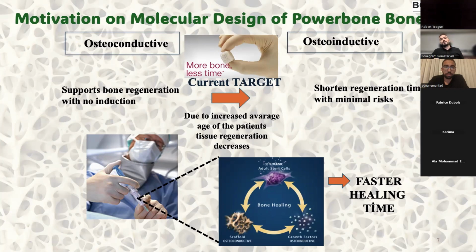In this regard, for osteoconductivity, to set the regeneration process adequately, beta-tricalcium phosphate is a great alternative. Among the other bioceramics, beta-TCP is considered one of the partially osteoinductive bioceramics. Why? Because the resorption time of beta-tricalcium phosphate is faster than hydroxyapatite.